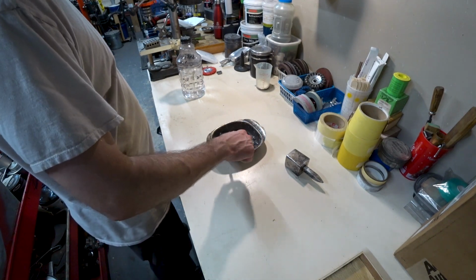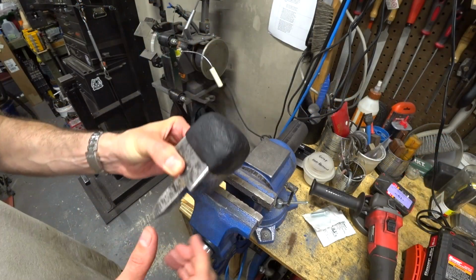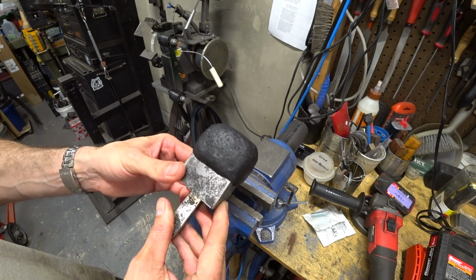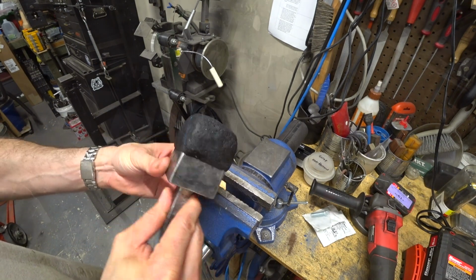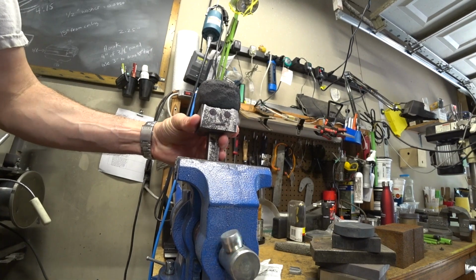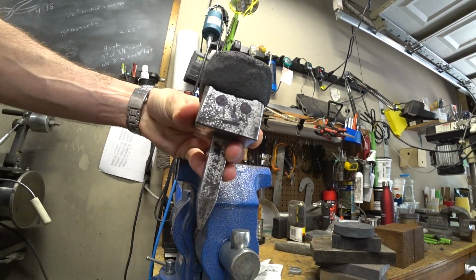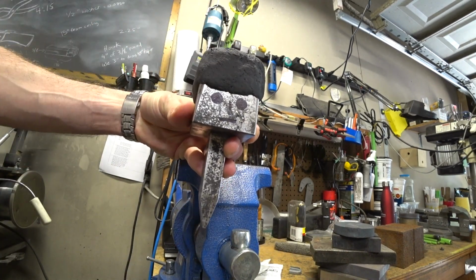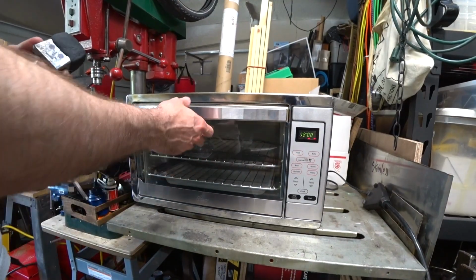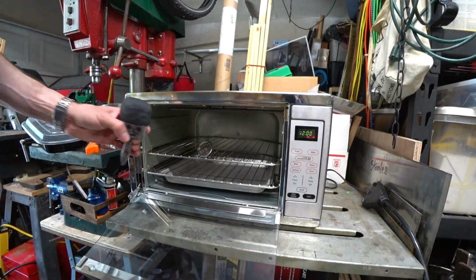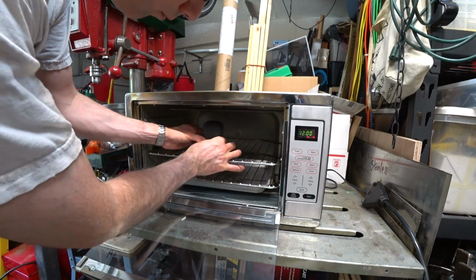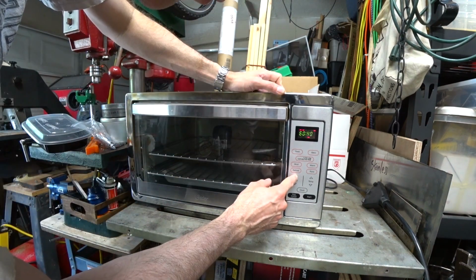My camera died without me realizing it, so I lost the footage of actually placing the compound. But you just want to put it over the top like a layer of clay. Lay it on about 1/4 to 1/2 inch thick. It looked a little like a bad wig, so you can see I drew a face on there. But anyway, I let it dry for a few hours, and then I put it in an oven at low heat to drive off the last of the moisture.